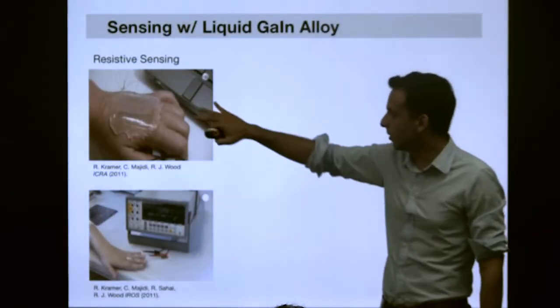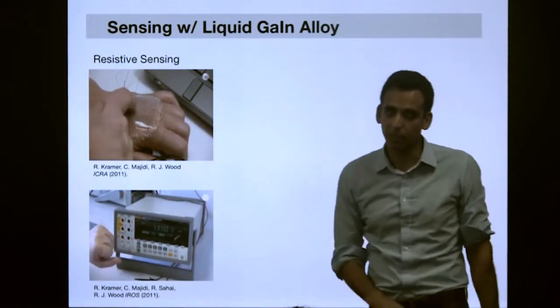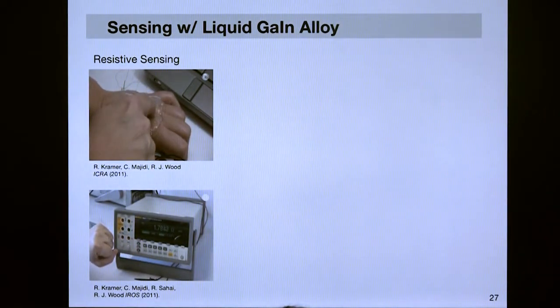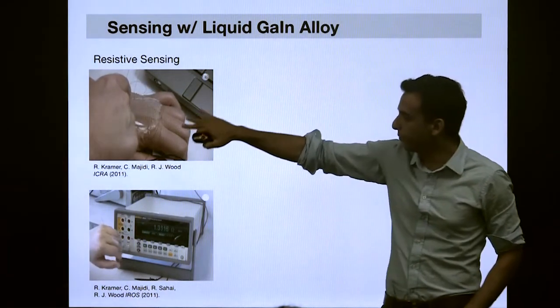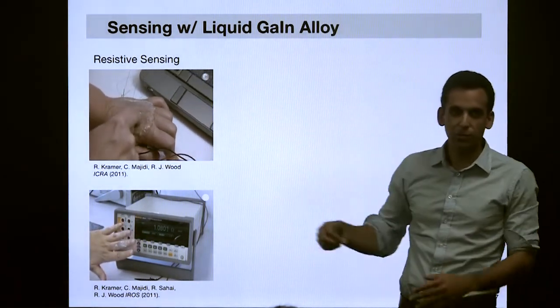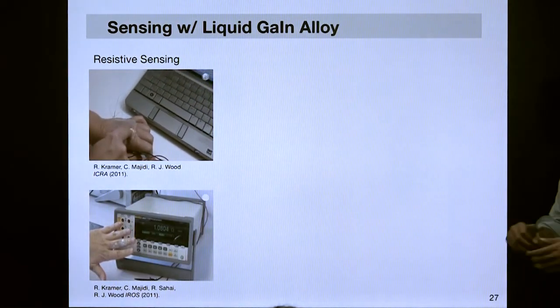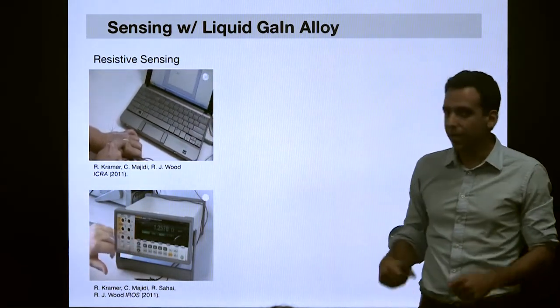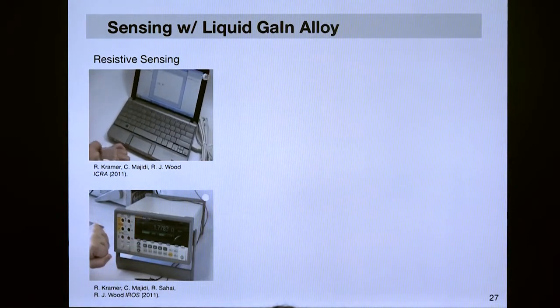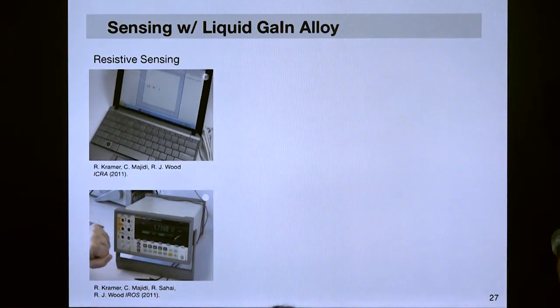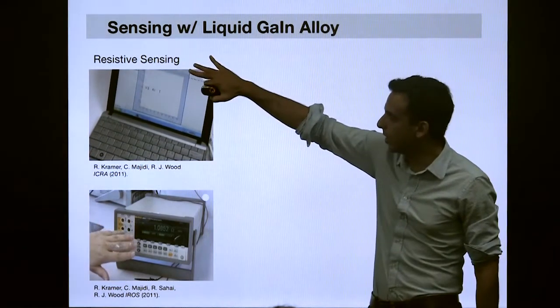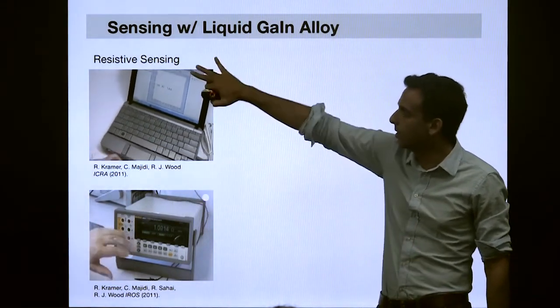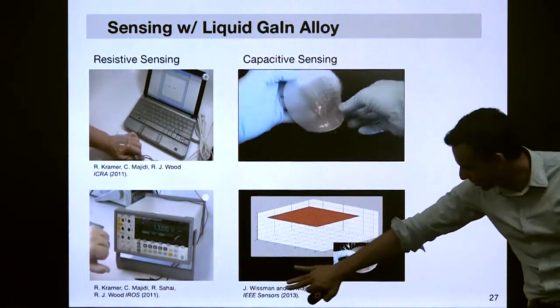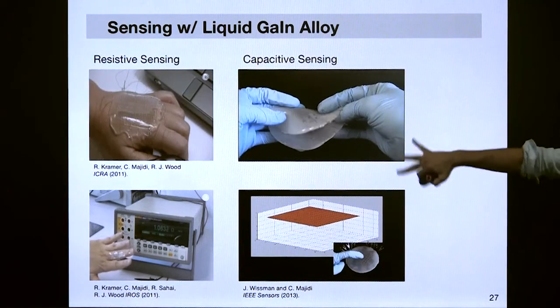Another interesting feature is that we have very strong electromechanical coupling, as you saw with that dielectric elastomer actuator. In this case, if we apply some surface traction, apply pressure, stretch, or bend these materials, that's going to change some of the circuit properties of those embedded liquid metal channels. So there's one coupling between elastic deformation and electric resistance. And this was done at a conference last year. Basically they made a capacitor array embedded in a soft material, and you see that there's an elastic deformation in this case.